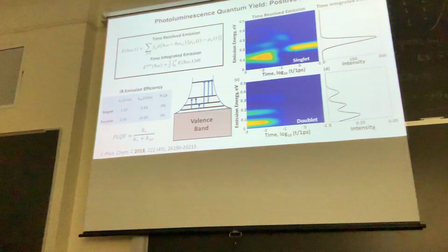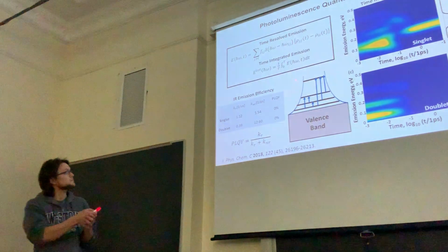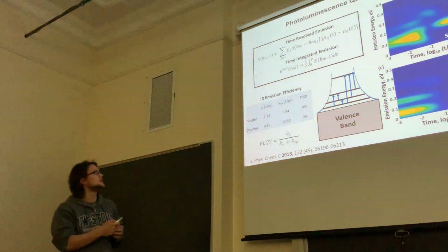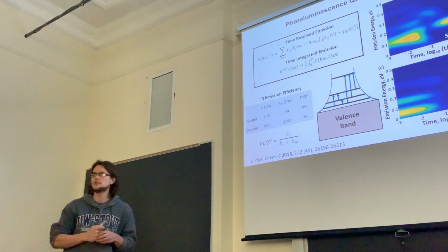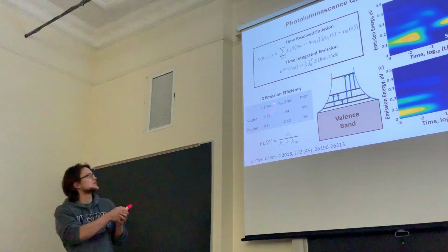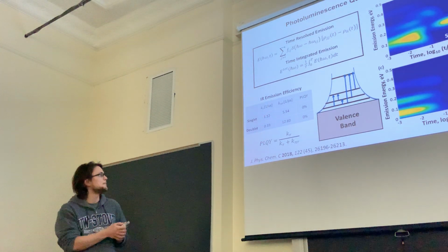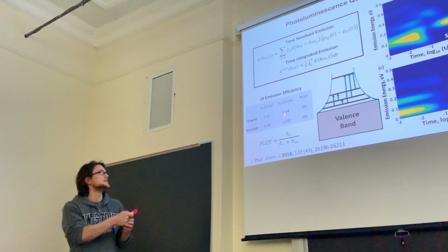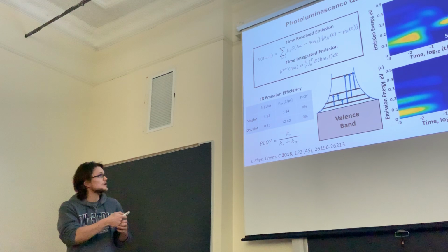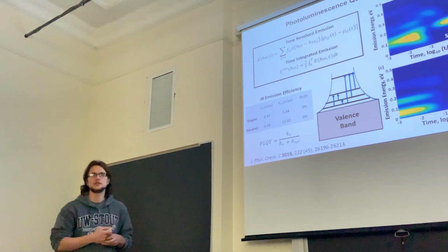And so the last slide is, if we consider how efficient these positive polaron emitters are. And so that's just summed up in this table. So this column corresponds to the radiative lifetimes, which just come from Einstein coefficients. And their rates occur on the inverse microsecond scale. Whereas for the non-radiative transitions, for that lowest energy transition, they correspond to inverse picoseconds.